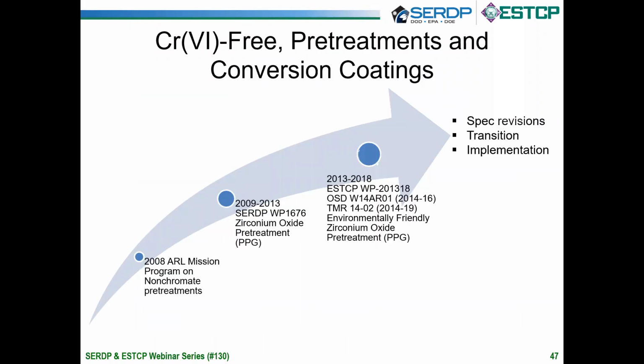And so some of the evolution of this project: way back in, I think, 2008 is when Fred came back to ARL, and one of the first things he began was to look at non-chrome pretreatments. This evolved into the 2009 zirconium oxide pretreatment, and then this successful program, which was co-funded by ESTCP, OSD, and Toxic Metal Reduction, the environmentally friendly zirconium oxide pretreatment.